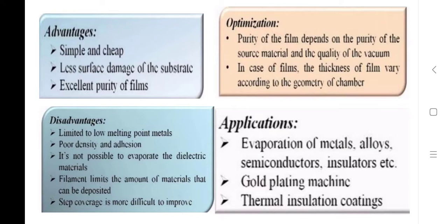Okay, then there are certain disadvantages also there. So this method is limited to low melting point metals, and it has poor density and adhesion. Okay, as I have mentioned, limited to low melting point metal and poor density and adhesion, because we are giving a certain heat in this particular method, and if the melting point of that precursor material is too high, then it is very difficult to make it into the vapor form.